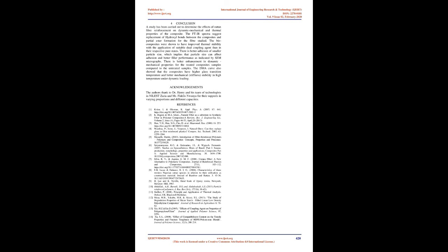There is better enhancement in dynamic mechanical properties for the treated composite samples compared to the untreated samples. The DMA curve also showed that the composites have higher glass transition temperature and better mechanical stiffness stability at high temperature under dynamic loading.